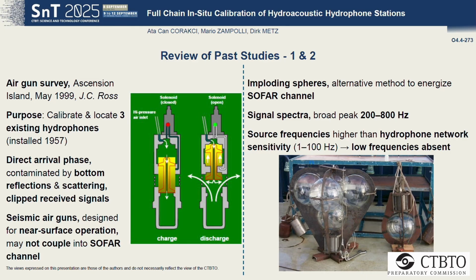So I just would like to briefly give some examples from not recent, but past studies. In the early 1990s and 2000s, there were a couple of experiments to check the full chain acoustic response of some stations. That happened in 1999, on the left, at Ascension Island, where seismic air guns were deployed to produce acoustic pulses. And these pulses were recorded by a calibrated hydrophone and compared with the station's hydrophone. This method was promising, but the implementation is not so easy because the direct acoustic arrivals were contaminated by strong seabed reflections, as the hydrophones in this case were positioned close to the ocean floor and the air guns were just below the sea surface.